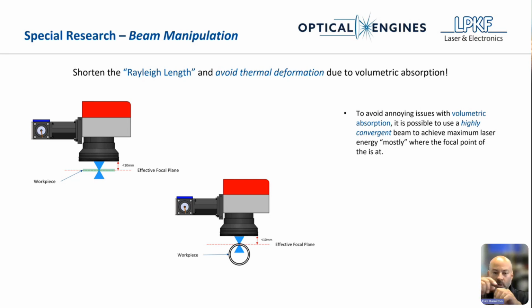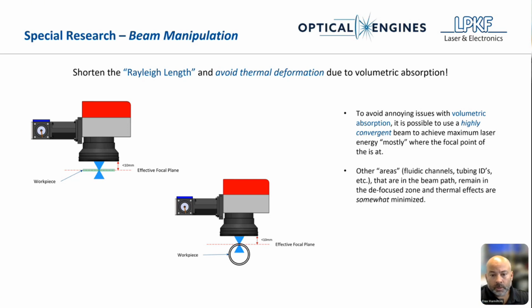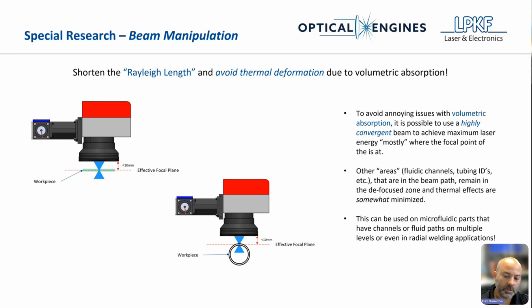So again, focusing right at that weld joint. In this case, it's a conical or radial weld. Let's say it's a tubing to fitting application. We focus that beam right down at the center point of welding. In some cases it's difficult to do because of clamping, because of machine structures, but thinking with this in mind, this can avoid a lot of issues if it's needed to have certain features or channels underneath or in the beam path of where the laser is going. So again, this will avoid thermal expansion of fluidic channels and tubing IDs, because it's staying in the defocus zone, and they can be somewhat minimized. It's not going to minimize all of it. Okay, that covers the main part of the technical side of it.